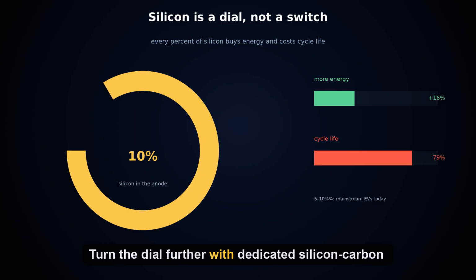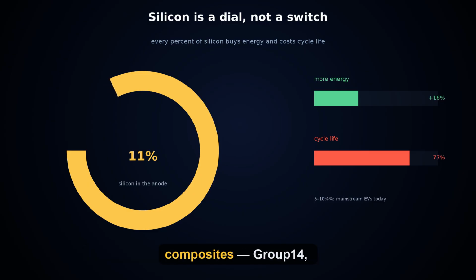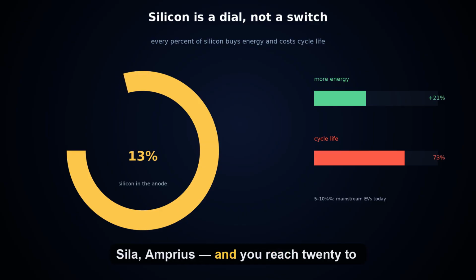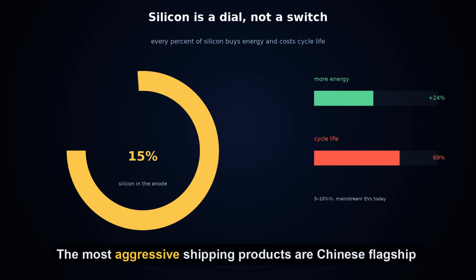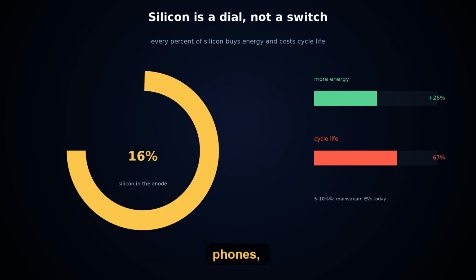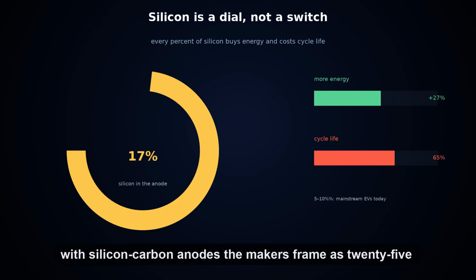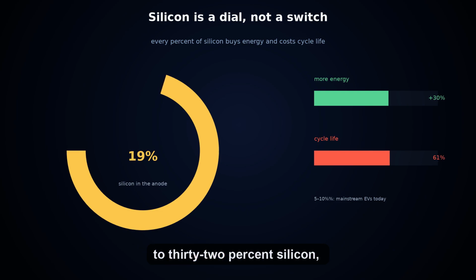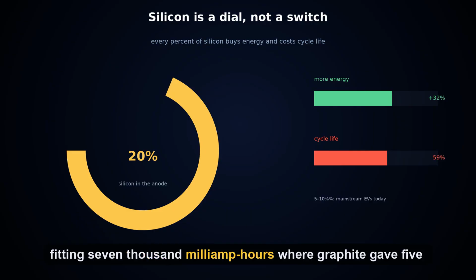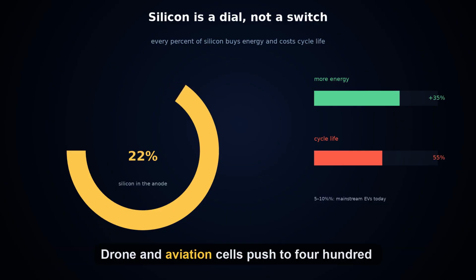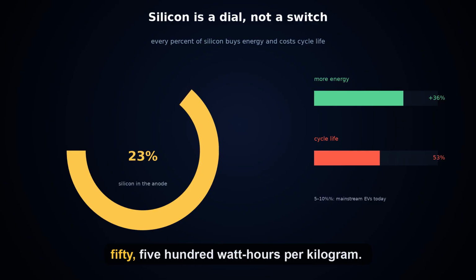Turn the dial further with dedicated silicon-carbon composites, Group14, Sila, Amprius, and you reach 20 to 50% more at the cell level. The most aggressive products are Chinese flagship phones. With silicon-carbon anodes, the maker's claim is 25 to 32% silicon, fitting 7,000 milliamp hours, where graphite gave 5,000. Drone and aviation cells push to 450, 500 watt-hours per kilogram.